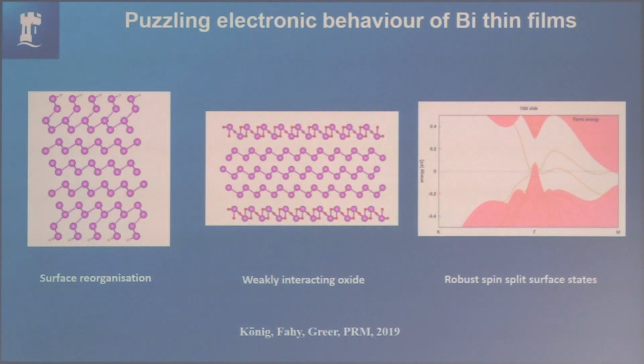However, when you start talking to people in the community, you go, well, of course, there are these well-known bismuth surface states. And we said, oh, okay. Yes, we knew there were well-known surface states, but we thought we had passivated. In other words, we thought we had eliminated the surface states. And this is where things get very complicated and quite a little bit challenging for us with bismuth anyway.